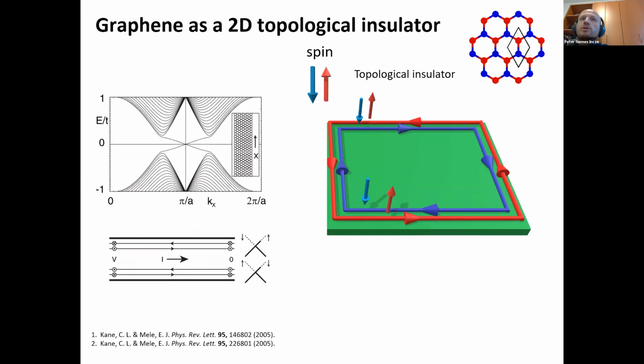I'm sure most of you know these famous papers by Kane and Mele, where they've shown that graphene is indeed the prototypical two-dimensional topological insulator, or as it's sometimes called, the quantum spin Hall system. So they have shown that if you switch on spin-orbit interaction, then the graphene band structure gets gapped, and you get these spin-polarized edge states, which are protected by time reversal symmetry.